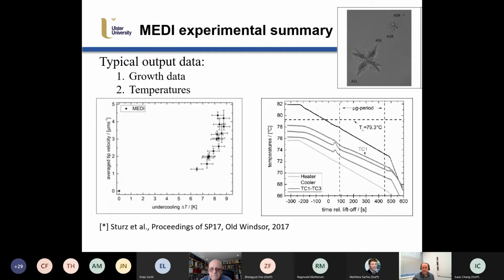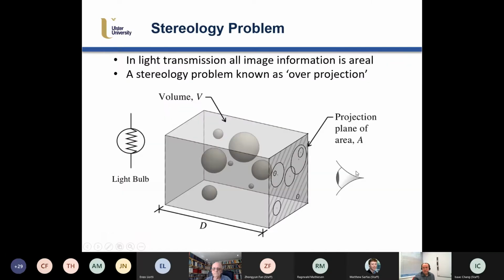They also had a nice optics system where they were able to zoom in and magnify individual crystals, and get some average tip velocity versus undercooling, again growing at around 6 to 8 Kelvin of undercooling. And because the thermocouples were inserted within the sample, they also have pretty good temperature data inside. One of the issues that we came across with this experiment is that the sample itself is around 3 millimeters thick in depth, so the crystals are much smaller than 3 millimeters.